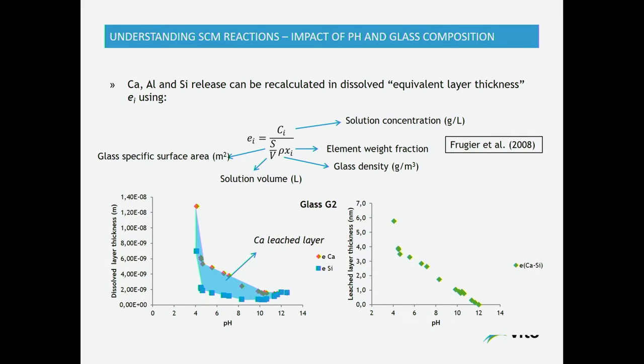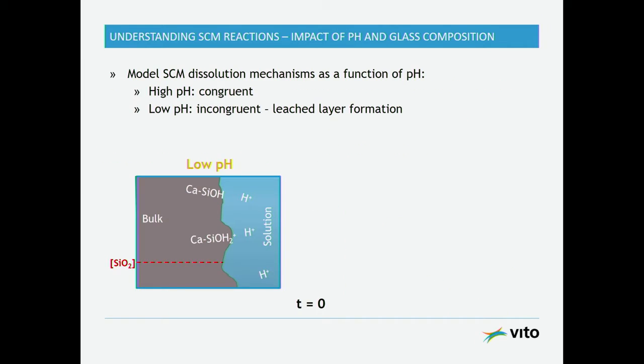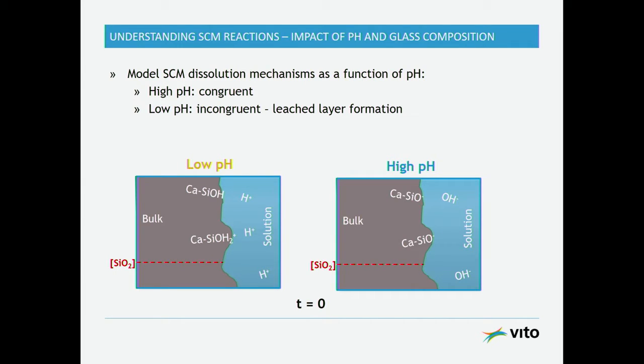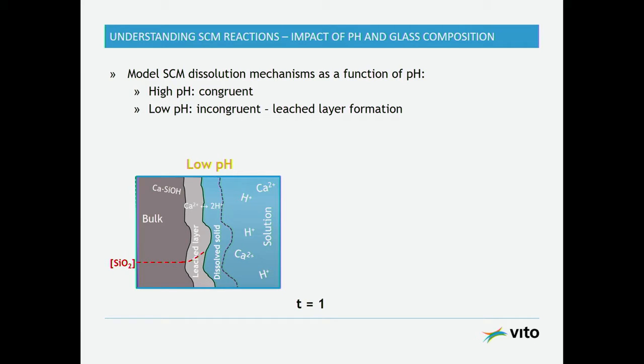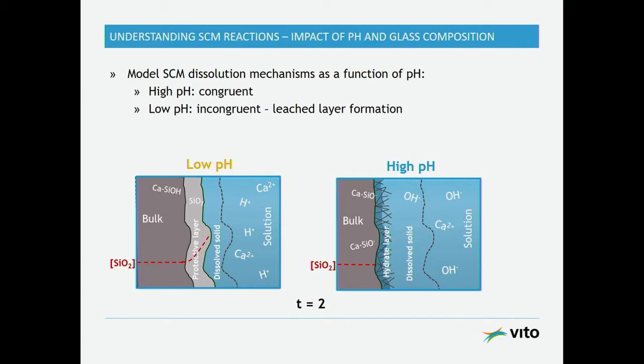This has also been shown here. So here you see then the calculation of the leached layer thickness with pH as well. So what we suspect is, at least for calcium, aluminum, and silicon, there is congruent dissolution at higher pH, but incongruent dissolution at lower pH. Taking these results, one can actually come forward with this kind of dissolution mechanism. So at low pH and high pH, we start here at time 0. And at low pH, we establish this kind of leached layer.